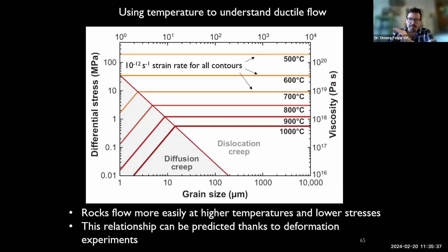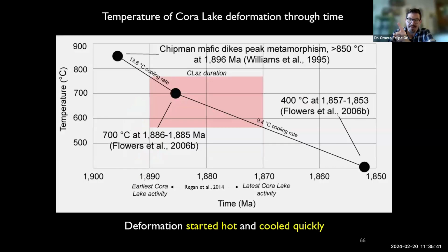And so this is important because you can mathematically model all this stuff. And we did it. And so the last little piece that we needed to do this proper full rheological model of the viscosity of our shear zone over its lifespan is the temperature, right? It's easy enough to say, look, there's garnets, look, there's CPX, so it must have been at least some degrees. But we can actually do better here because of all the work that's been done in this particular area. The thermal history of this shear zone can be pretty well constrained by showing that there's this whole set of mafic dikes, which is a fascinating, crazy thing all in itself, that predated this shear zone by not that much, and just turned everything into mush. It cooked the dickens out of this whole region, all these mafic dikes everywhere. And so the temperature everywhere just went really, really high.